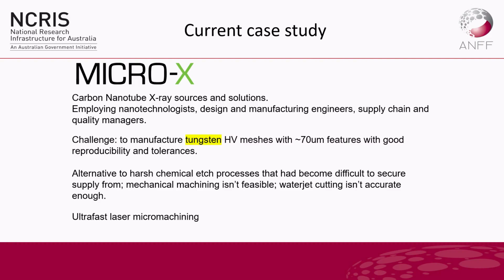They're down at Tonsley. Microex has been working for a good long time on really compact, novel X-ray sources. As X-ray detectors have gotten much, much better, the X-ray emitter can be scaled down and actually use some pretty novel materials like carbon nanotubes as the emitting material. But the one thing that your X-ray tube does need is a high voltage mesh, a high tension mesh or a screening mesh. And that needs to be cut from tungsten so that it survives all the electron current in the vacuum tube. Machining tungsten is not fun.